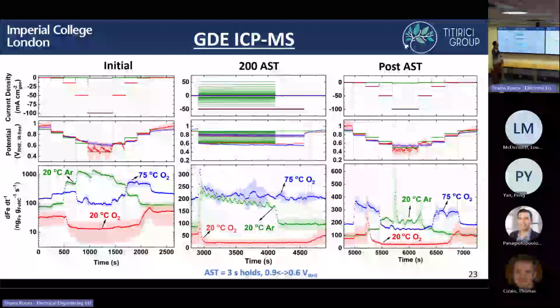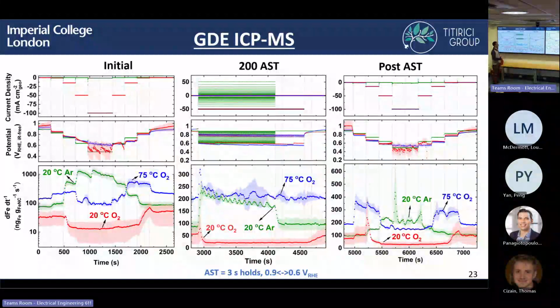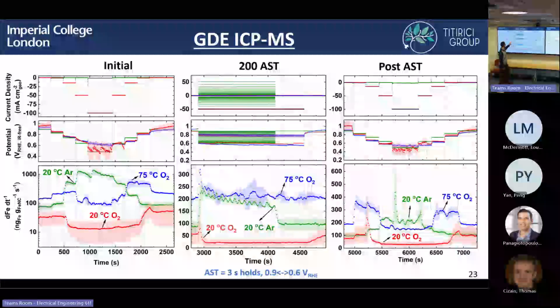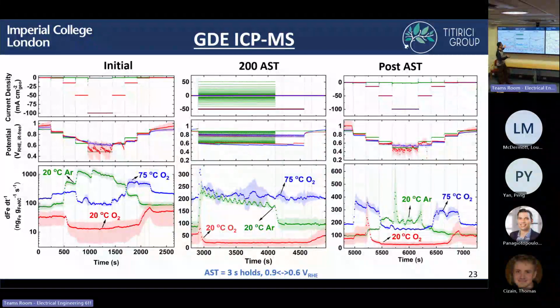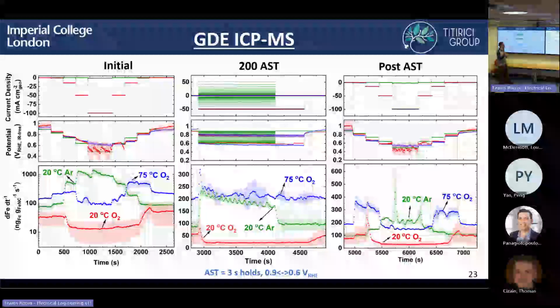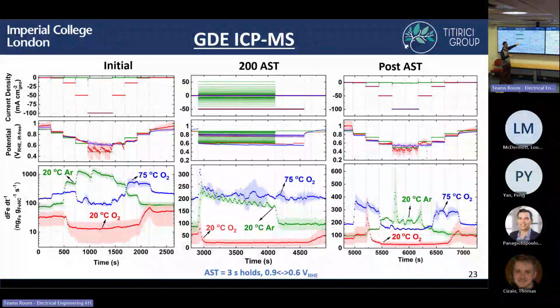And finally, if you then do the measurement after the AST, so same as this measurement, but you've just done the AST, again, you see a similar sort of thing to here, except some parts are exaggerated. And this is, we think, because of a buildup of iron oxide in the catalyst layer during this AST.